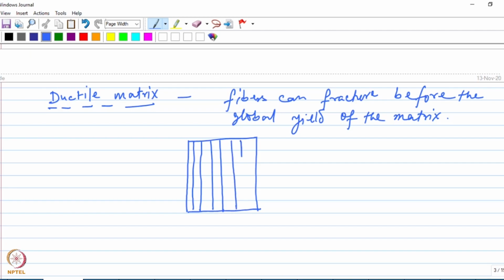So let us consider a fiber reinforced composite like this. So what we are saying is the fibers will be broken. The fiber will fracture first, and how this crack will propagate, that depends on the bonding at the interface. Okay, so this is the interface that you have over here, right? So this interface, how it behaves, depending on that, the propagation of the crack would vary. Okay, so again here also we can make distinction between two cases. One when the interface bonding is strong, and the other when the interface is weak.